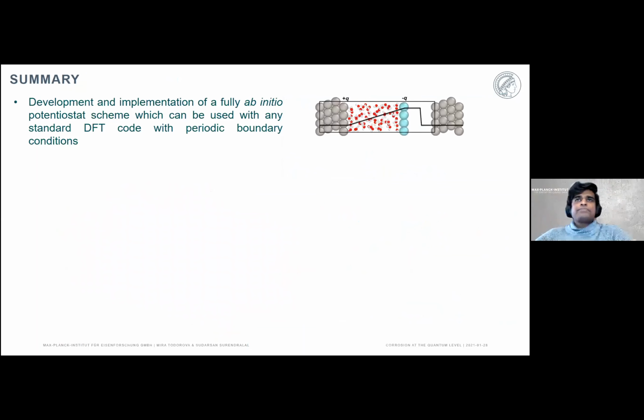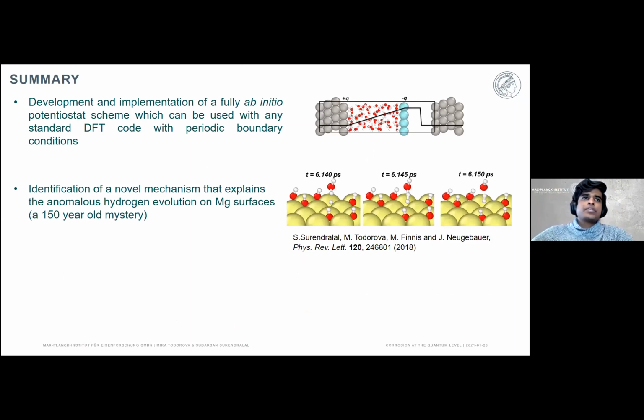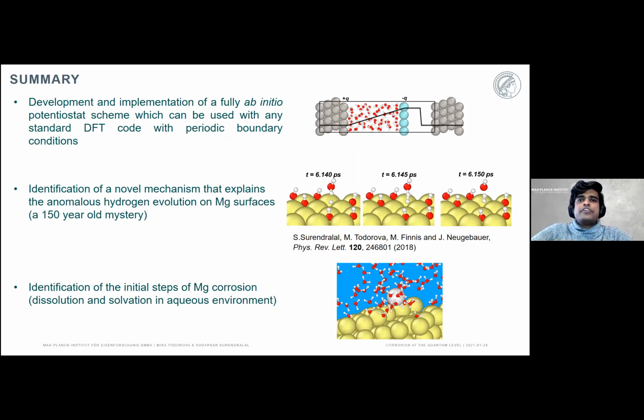So in conclusion of my portion of the talk, I've showed you basically how we've developed and implemented a fully ab initio potentiostat scheme, which can be used with any density functional theory code with periodic boundary conditions. Using such a potentiostat, I hope I've been able to demonstrate how we identify a novel reaction mechanism for the hydrogen evolution on magnesium under anodic conditions. And finally, we use it to identify the initial steps of magnesium corrosion in an aqueous environment.